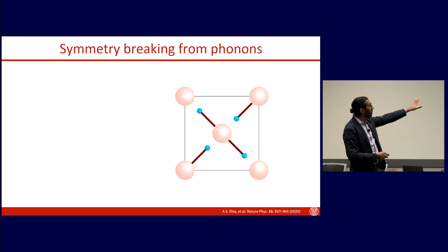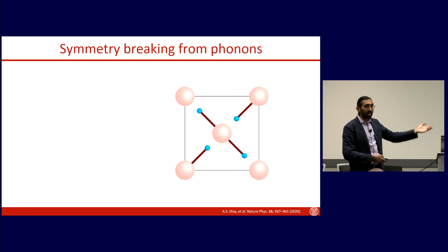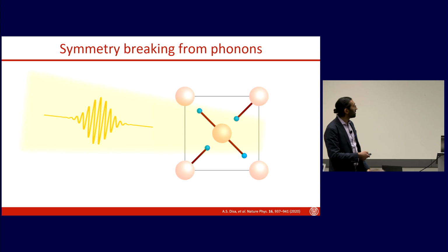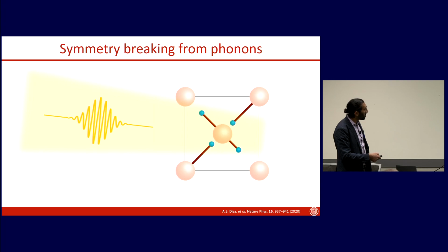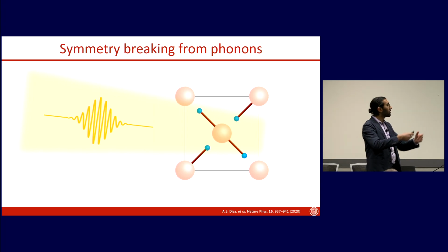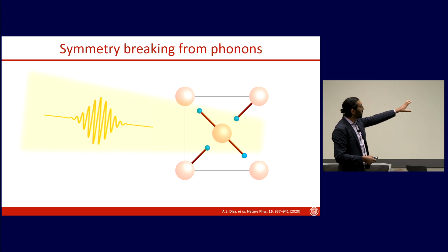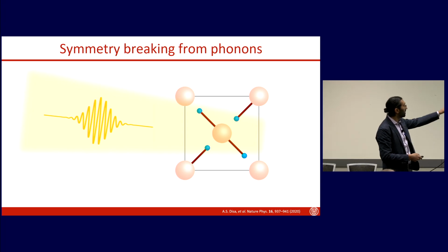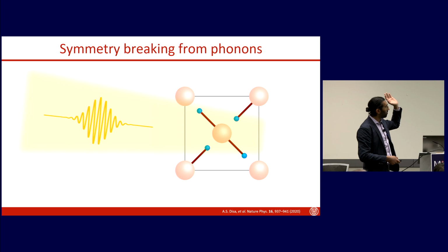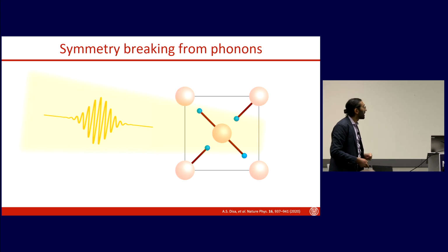Okay? And this is the effect that we use to try to achieve this Raman distortion that I talked about before. I'll just show you what the end result is. Basically, I'm just showing you a simulation of what happens when I actually excite a particular infrared active mode, which is coupled to this Raman mode. And what happens is that I excite this infrared active mode that's wobbling back and forth. But you can see that in addition, there's this displacement of these bonds. Like that one only goes up, and on average, this one only goes down. And so in addition to the vibration of this infrared active mode, you have this Raman displacement. Okay, so this is what's happening when I shine my light that's, let's say, resonant with some infrared active modes to very high amplitude.